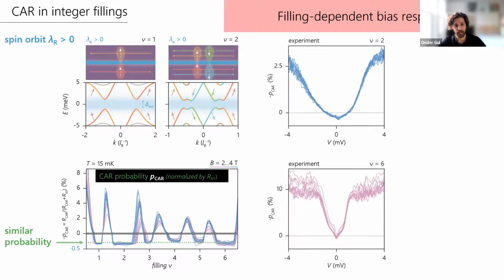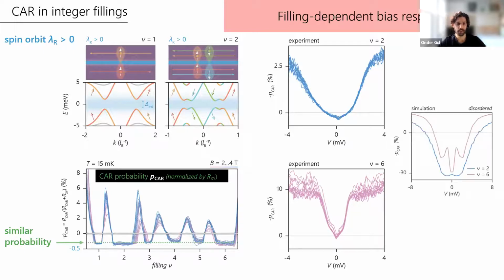So the similarity in CAR probability that you see is limited to small energies, however. Increasing the bias voltage provides distinguishing features which are reproduced in the simulations. Simulations suggest that filling-dependent bias response is related to smaller fillings having edge modes closer to the superconductor, which then pair more strongly. Okay, here you can see in the simulation that the negative range of filling factor 2 and 6 are different.